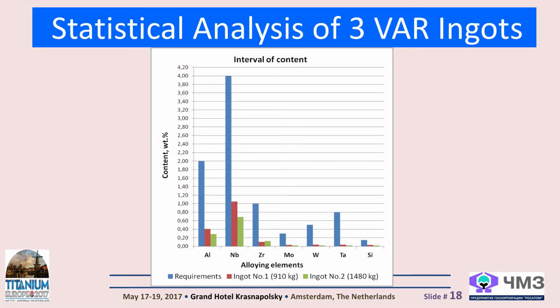To assess the uniformity of the alloying elements distribution along the height of the ingots, the statistical analysis of the results was carried out using standard parameters. They are also on the slide: range of dispersion of the values, standard deviation, and coefficient of variation. They are given in this table. It should be noted, the main thing to pay attention to is the narrow intervals of variation, the range in red color, of actual data in comparison with those established there in the upper line. And this applies both to alloying elements with a high content, niobium and aluminum, you see, niobium 38-42% and aluminum 10-12%, and also the elements with small consumption, silicon and molybdenum.